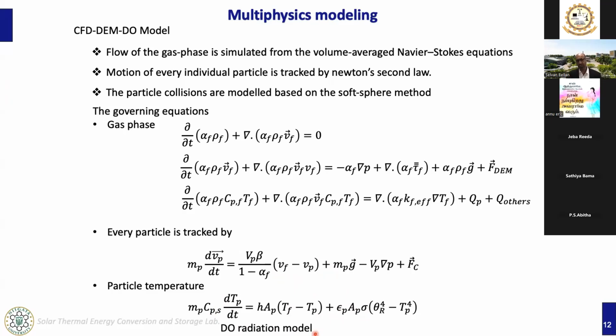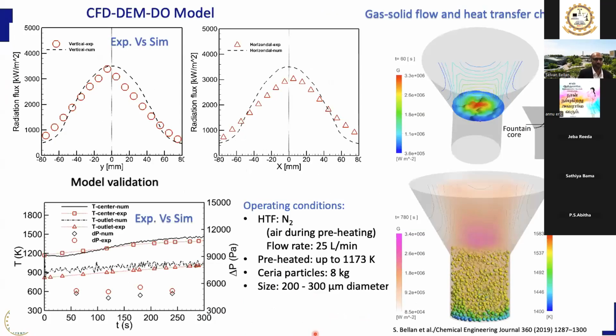So we developed the model, and then to verify and validate it, we performed experiments for the operating conditions shown here, and we did simulations as well. The experimentally measured and numerically predicted radiation distributions along the vertical and horizontal planes, in the focal plane, are compared here. As you can see, a reasonable agreement has been achieved between the simulation and experimental results.